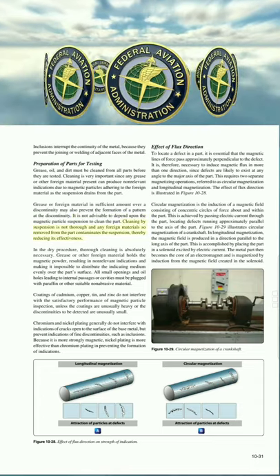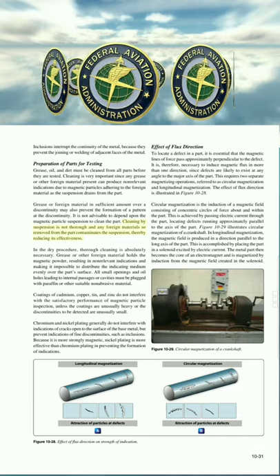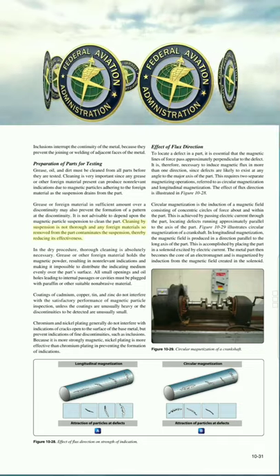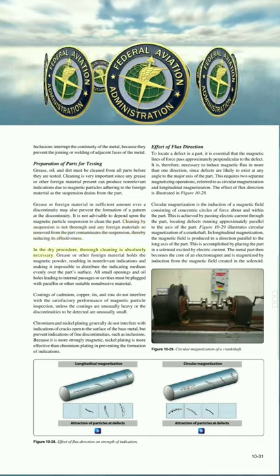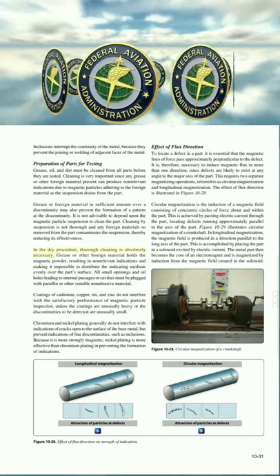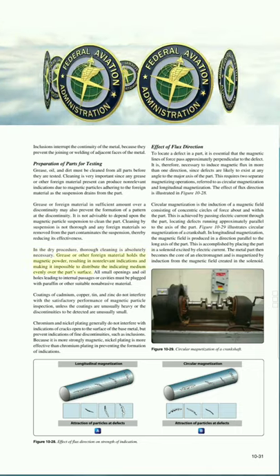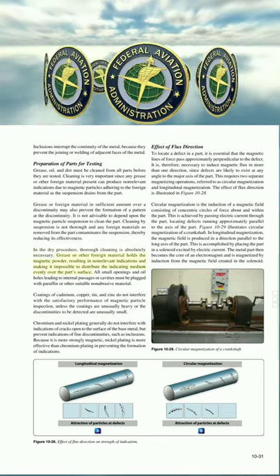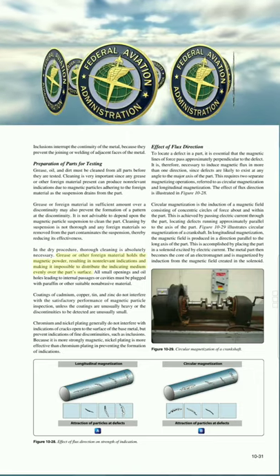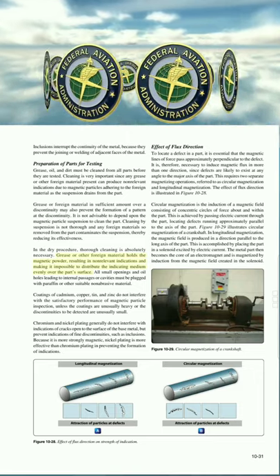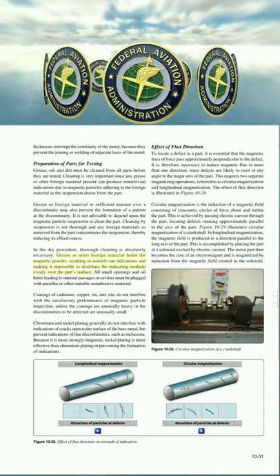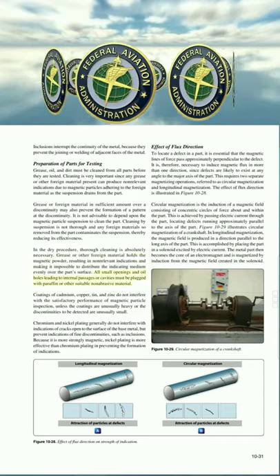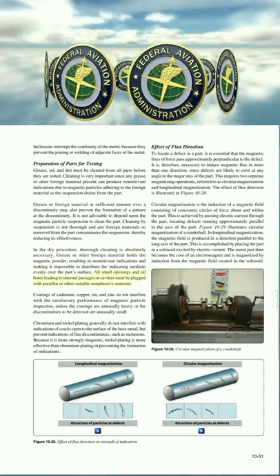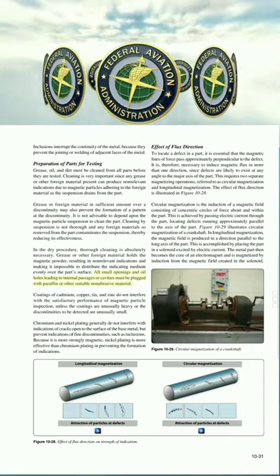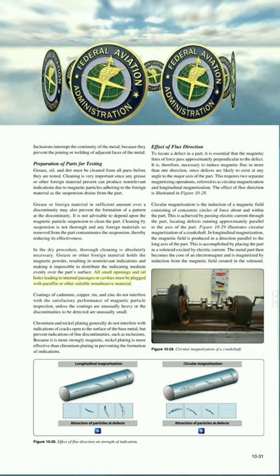Cleaning by suspension is not thorough and any foreign material so removed from the part contaminates the suspension, thereby reducing its effectiveness. In the dry procedure, thorough cleaning is absolutely necessary. Grease or other foreign material holds the magnetic powder, resulting in non-relevant indications, and making it impossible to distribute the indicating medium evenly over the part's surface. All small openings and oil holes leading to internal passages or cavities must be plugged with paraffin, or other suitable non-abrasive material.